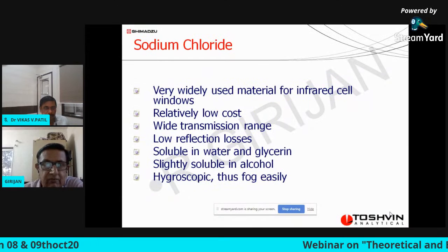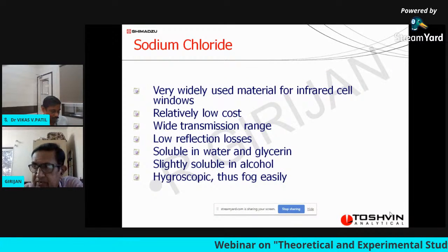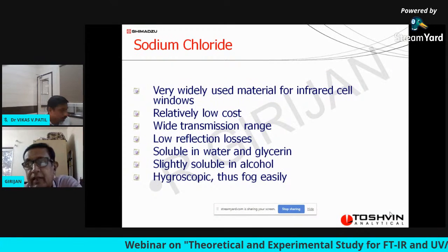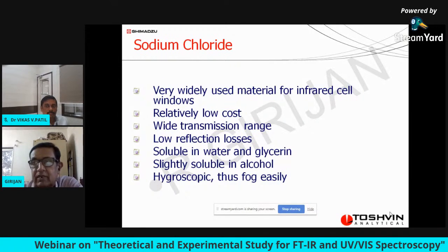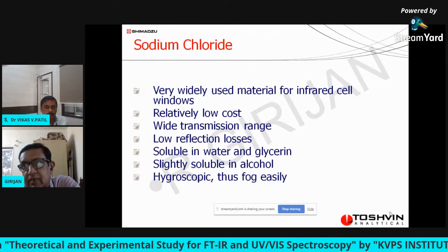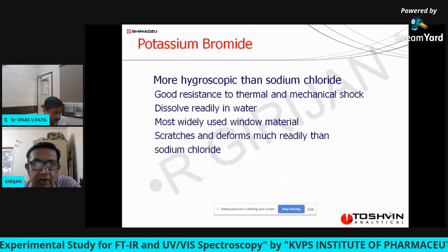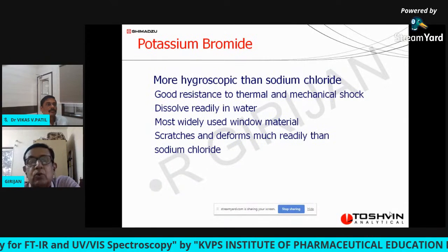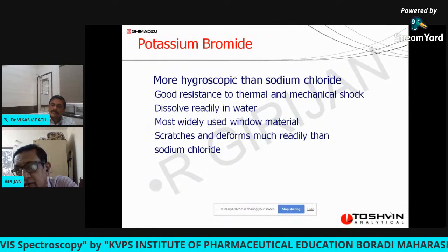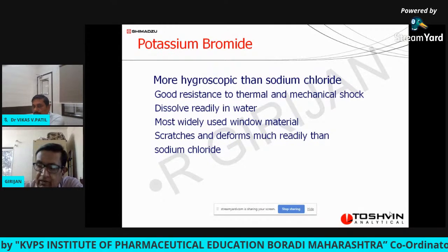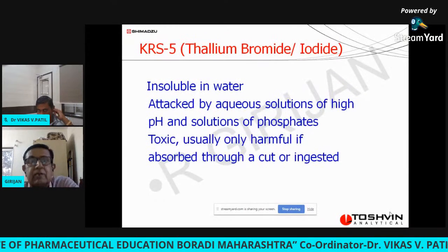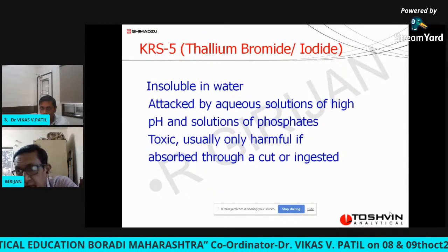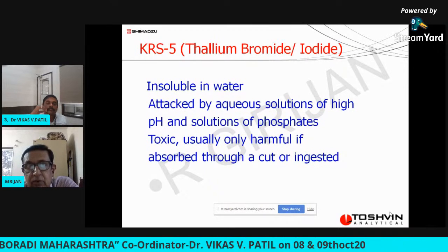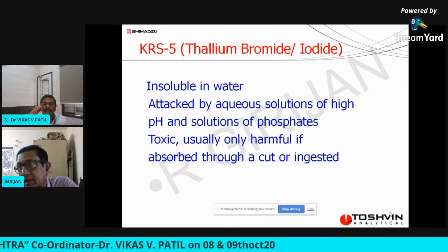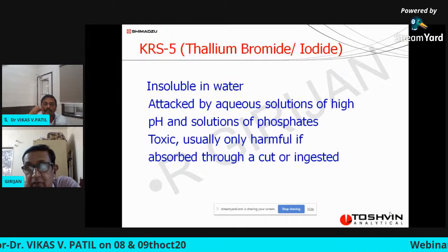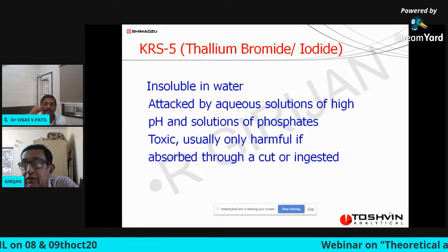Sodium chloride is not very expensive, but this window can be used only up to 600 inverse centimeter. From 4,000 to 600 inverse centimeter you can use sodium chloride. Potassium bromide you can use from 4,000 to 400 inverse centimeter. Then there is another excellent window called KRS5, which is a 1:1 mixture of thallium bromide and thallium iodide. And this can be used up to 215 inverse centimeter.